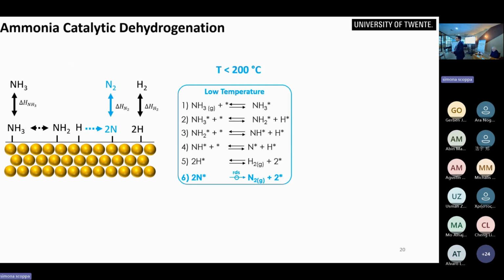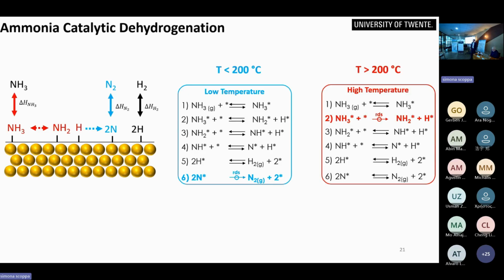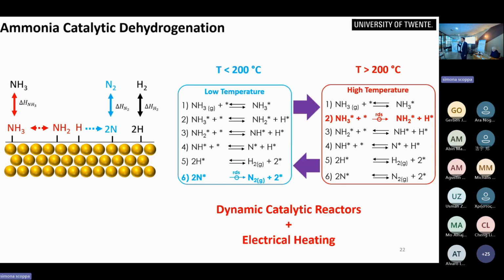Now, to develop this, we have to go to the basics. So if you look at the reaction scheme of the ammonia cracking, you see that the first thing that happens is ammonia adsorption. And in this process, it is well known that the nitrogen-hydrogen bond dissociation is a rate limiting step at high temperatures. But if you are working at low temperatures, then it's a nitrogen-nitrogen bond recombination, the rate limiting step. Essentially, the surface is covered by nitrogen, and now you are sort of nitrogen inhibited, not poison, as it was mentioned earlier. And at high temperatures, it's actually the nitrogen-hydrogen bond dissociation. So the underlying question that we have for this project was, can we actually go back and forth between these two rate limiting steps in such a way that we can enhance the overall reaction rate?